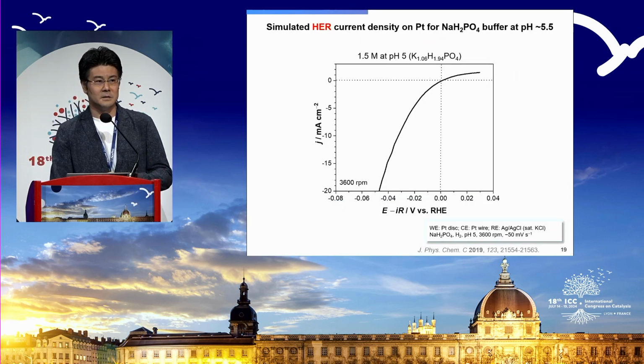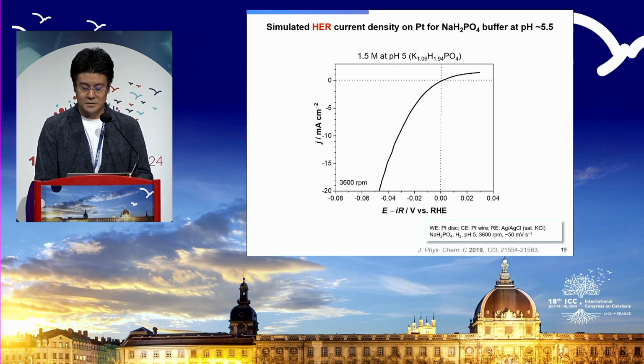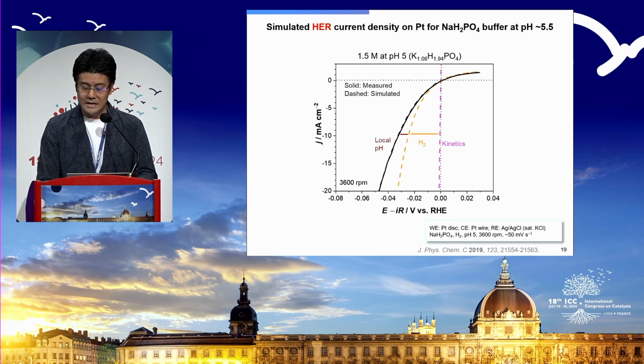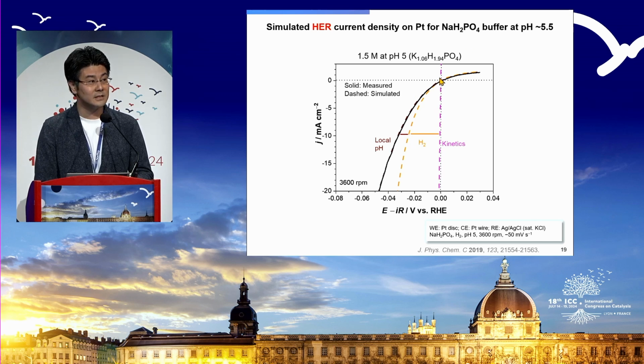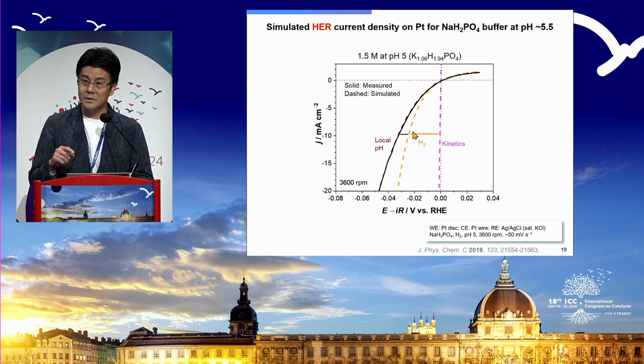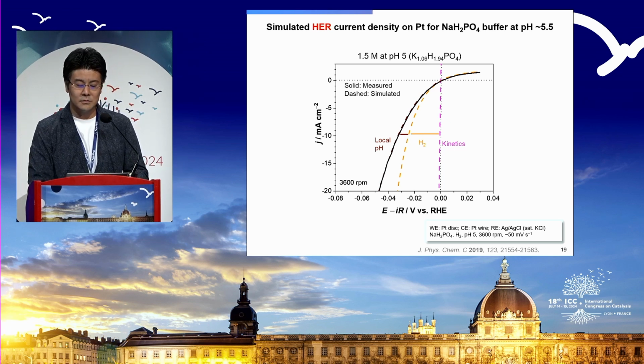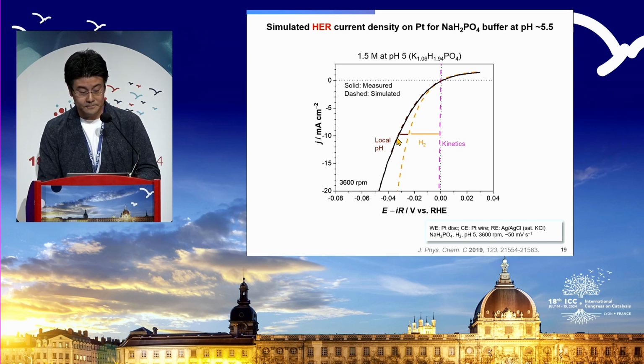And what you will see in these buffering conditions is that the overpotential of hydrogen is actually not coming from the platinum kinetics. Platinum kinetics is so good that it appears as if it is on the y-axis. The additional overpotential in this particular case comes from the hydrogen evolved escaping from the electrode, because in these conditions hydrogen oxidation also occurs. And additionally, this is the buffer contribution that cannot be eliminated compared to acidic conditions. So this is a local pH shift that we observe.